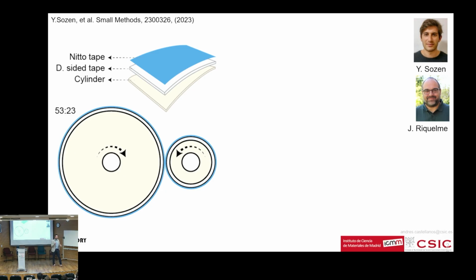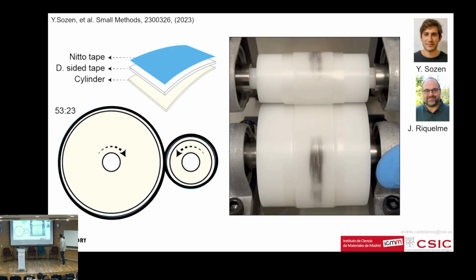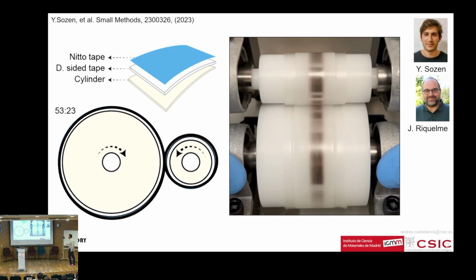They're rolling on each other. Before starting the rolling, we place a bulk single crystal on one of the cylinders, and then we start the rolling. The rolling is going to cleave the crystals and spread them all over the tape. Actually, it's because of these 2 big prime numbers that we get a homogeneous spread. So I'm giving you already some hints. And the process right now looks a little bit like this.